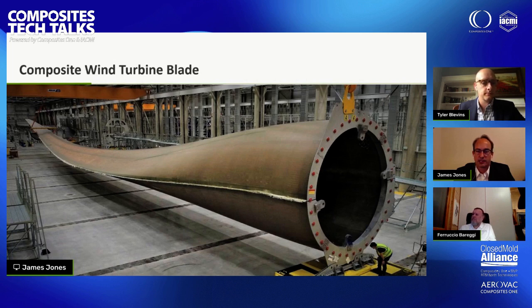Modern wind turbine blades, as I mentioned, are growing longer, over 100 meters, as pictured in this blade on the screen, so over 350 feet long. They weigh up to 55 metric tons or 120,000 pounds. And that's about 60% fiberglass or carbon fiber, about 30% epoxy or polyester resin, and the rest is core material, adhesives, and hardware.